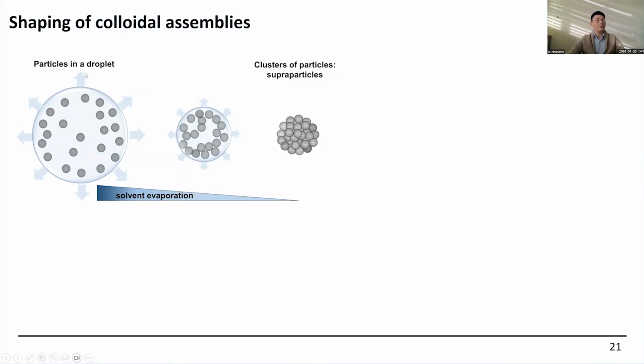Briefly speaking, we have the nanoparticles or nano building blocks inside the droplets. And during the droplet solvent evaporation, these nanoparticles will self-assemble together into a spherical shape to minimize the energy. And because they are made from nanoparticles, we call this assembled structure a supraparticle.